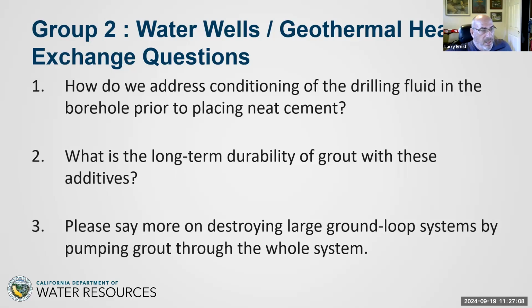But it seems like unless you have a flowing artesian well, you should be able to put some parameters in the standards to say that your well should have, there's very few circumstances where the viscosity should ever be over about 45 seconds per quart or 9.5 pounds per gallon, which are way over what I would normally specify. But I believe you could pump neat cement through that. But there's got to be some standards to address the conditions of the fluids above your TAC in order to make this work. Yeah, absolutely. Well, I completely agree with you, Larry, in principle. I defer to you on the actual numbers that you may want to put into the document. I'd be happy to provide more information to DWR if you want to add that information in. Excellent. Thank you both.